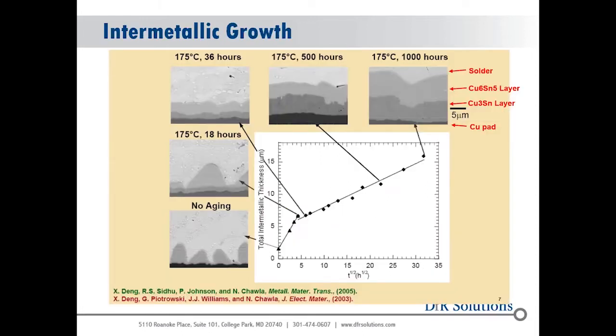As it gets thicker and thicker, if you look at this type of chart or these actual pictures of the intermetallic growth of tin copper intermetallics, if you can imagine I had a crack and it wants to crack through this intermetallic here on the lower left-hand corner, as the crack propagates through the intermetallic, it's going to hit ductile solder regions and it's going to be arrested, and it's going to have to sort of work its way through the plastic material before it hits the brittle material.